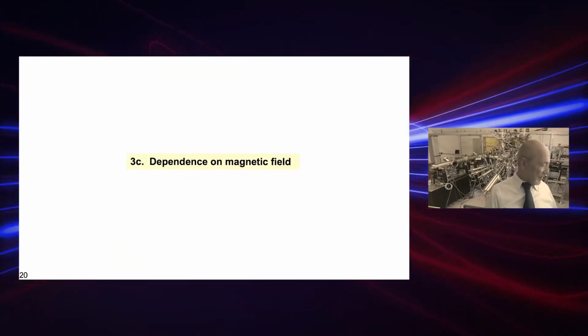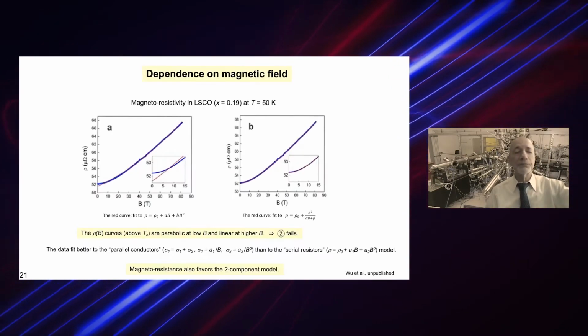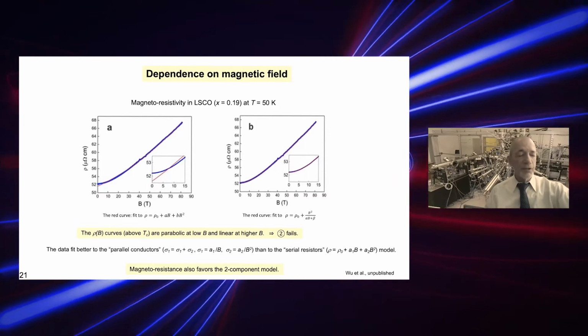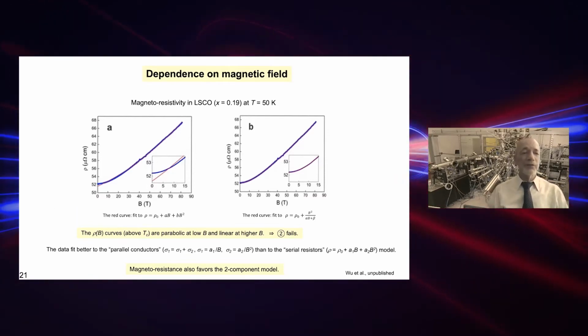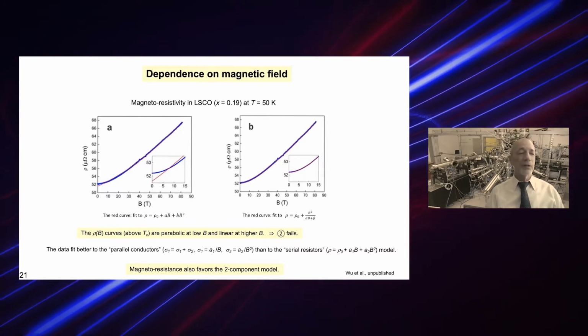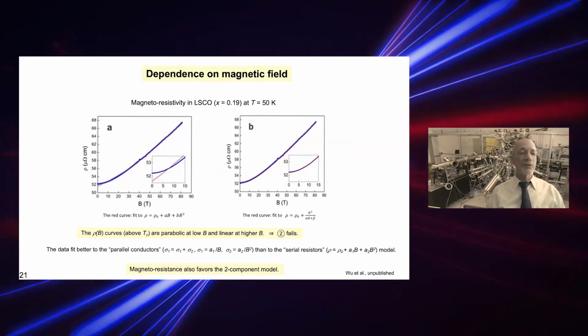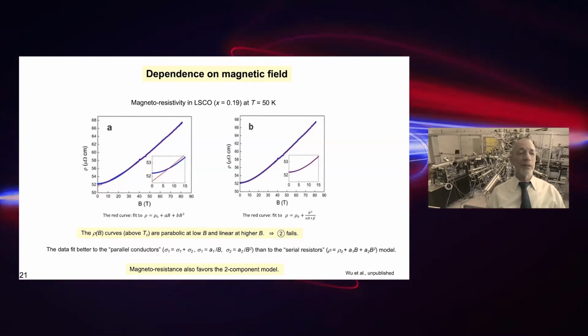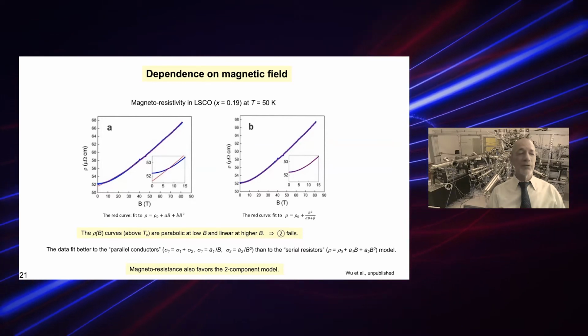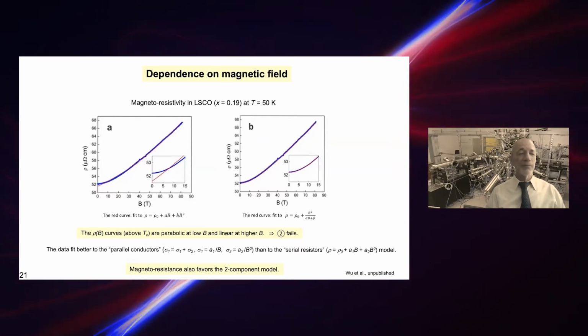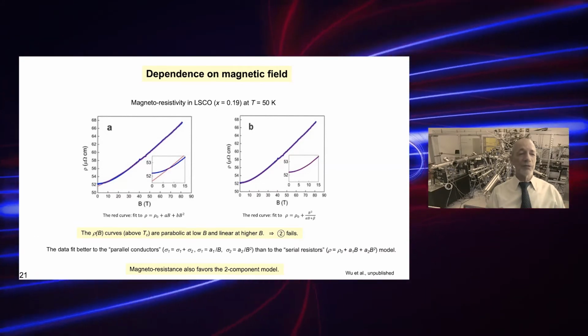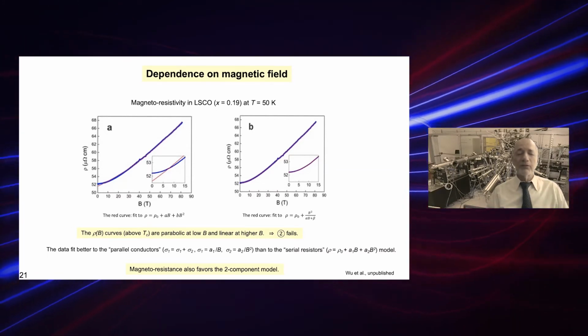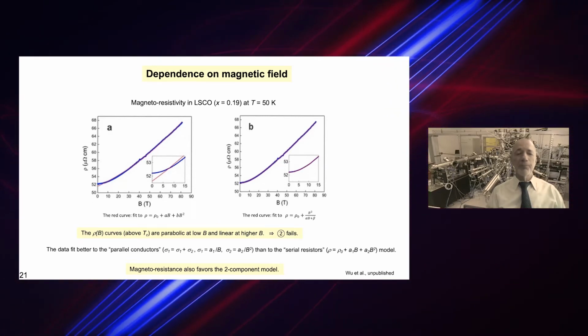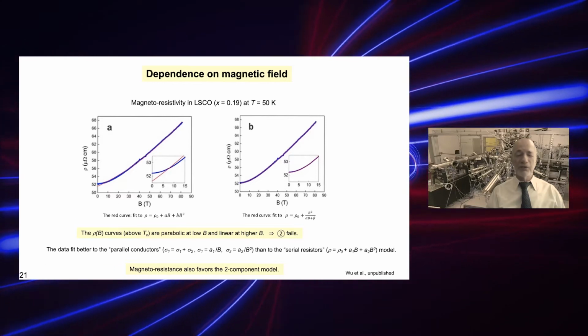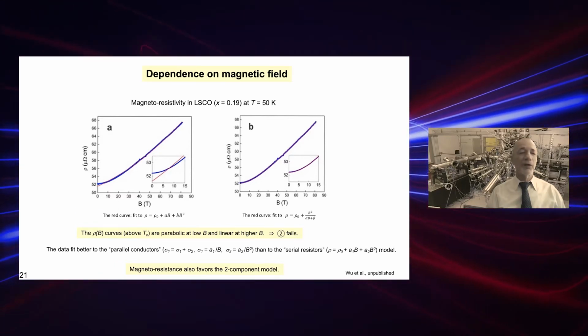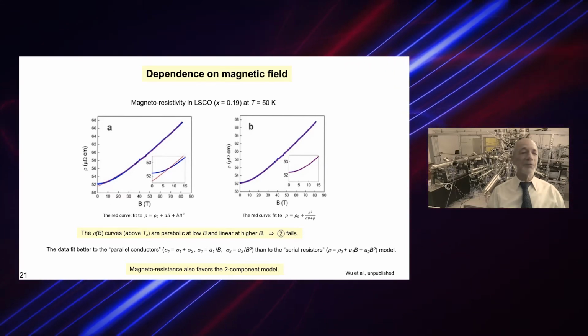Let me turn now to the magnetic field dependence. So in the literature, magnetoresistivity data are also typically fit to a serial resistance model, which will be applicable if you have a single carrier species that encounters two or more different sources of scattering. One of these has to give this linear in field dependence, which is mysterious, strange, unexpected in Fermi liquid theory. And you would need to explain that.